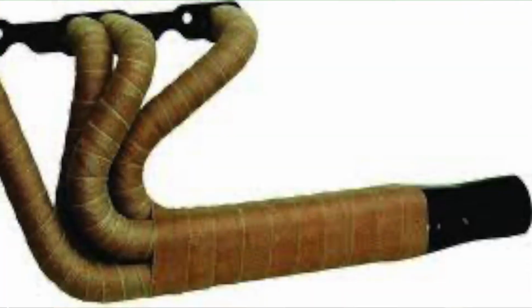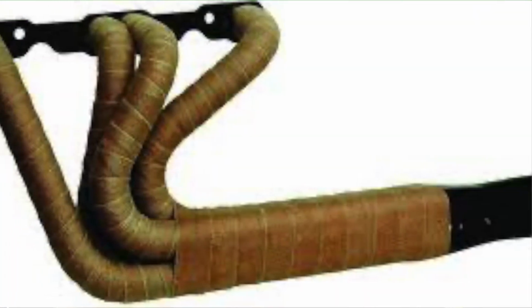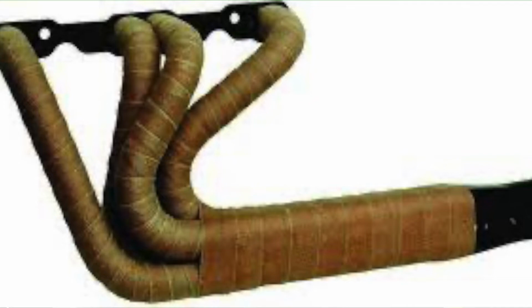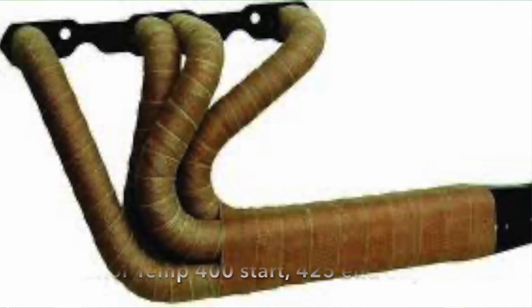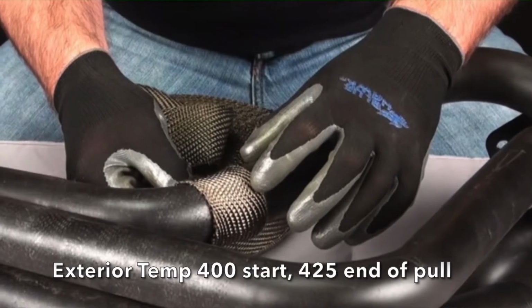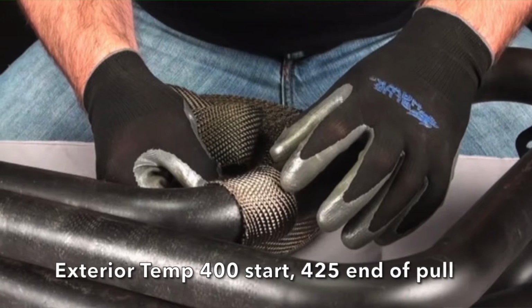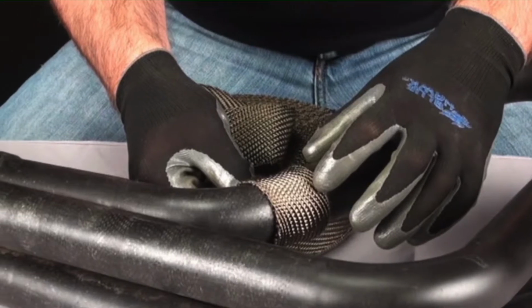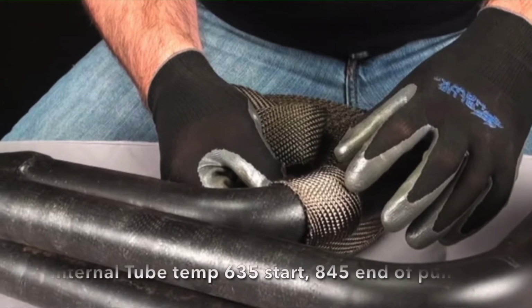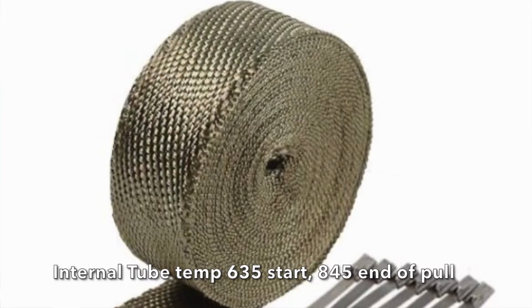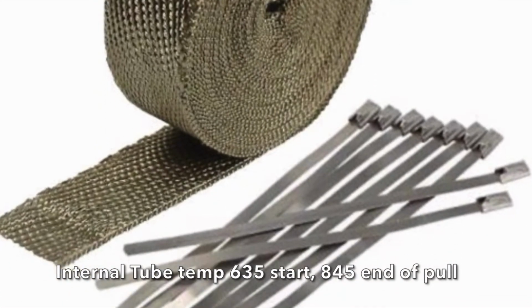And finally, the wrapped header, the header that has the external wrapping all the way around it. It started also with an exterior temperature of 400 degrees. It only went up to 425 degrees by 6,800 RPMs on the dyno pull, and the exhaust gas temperature started at 635 degrees and went up to 845.